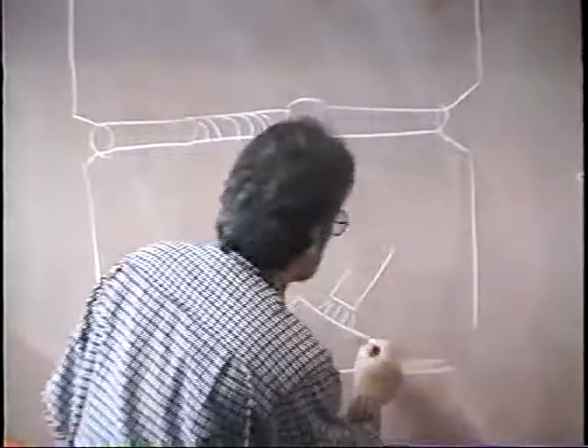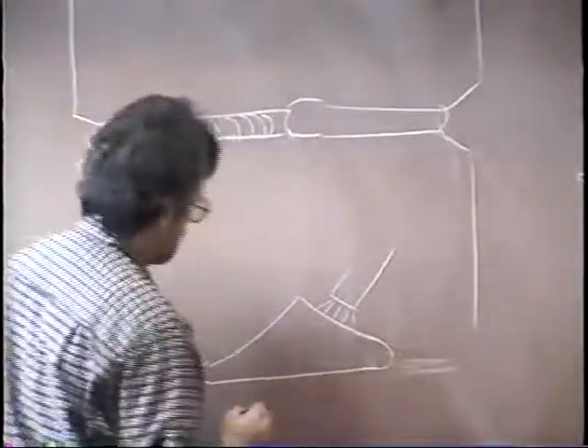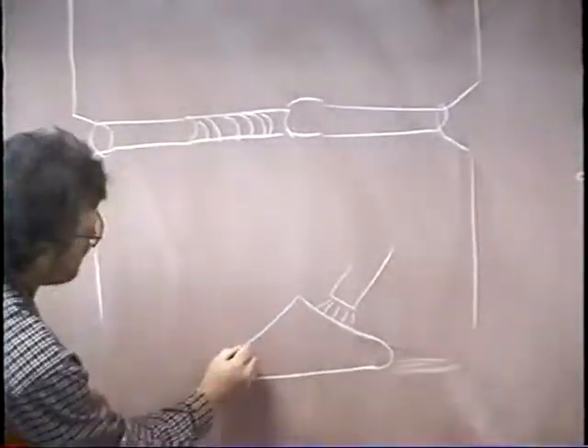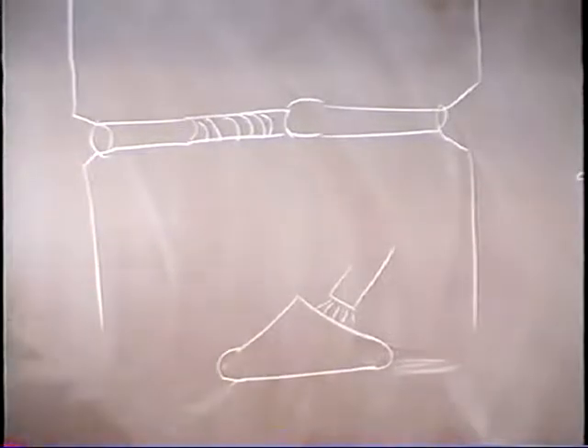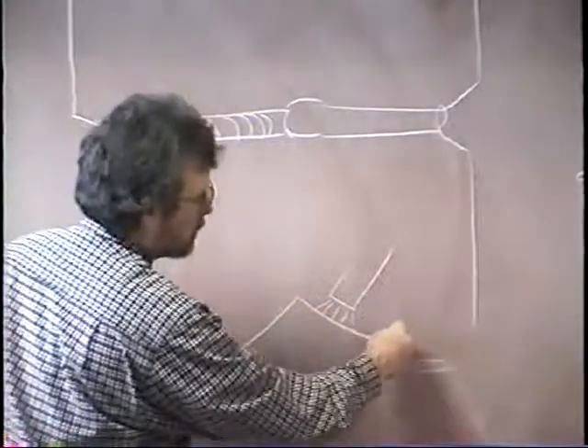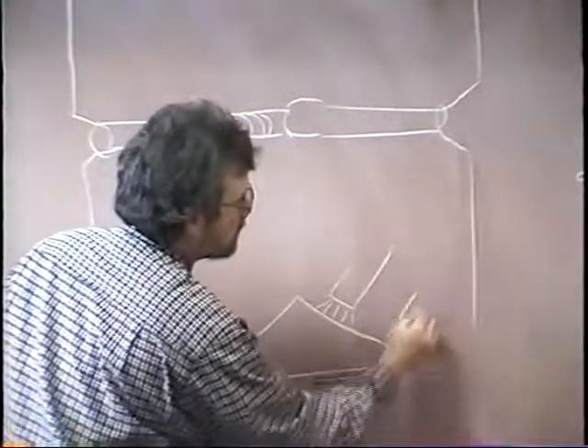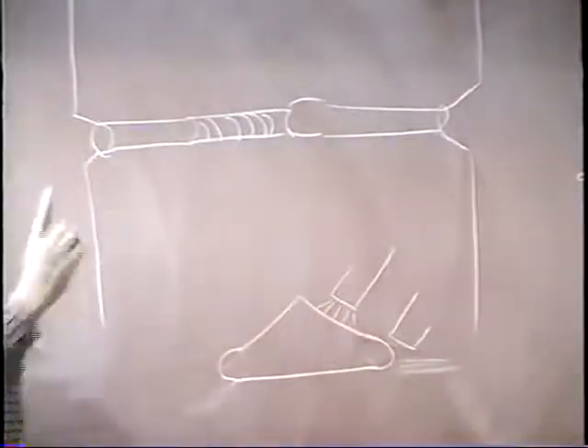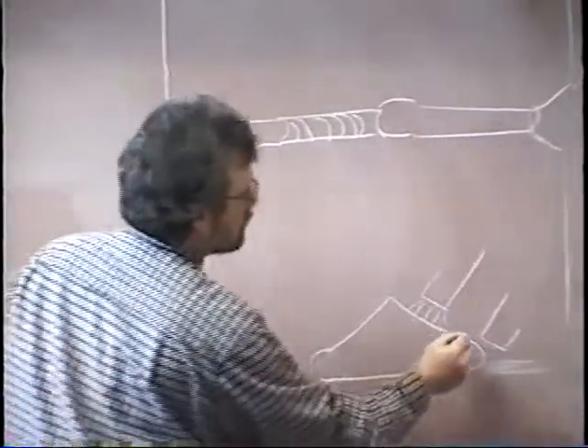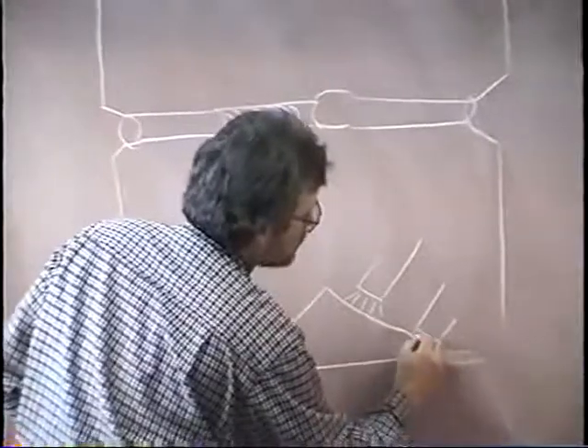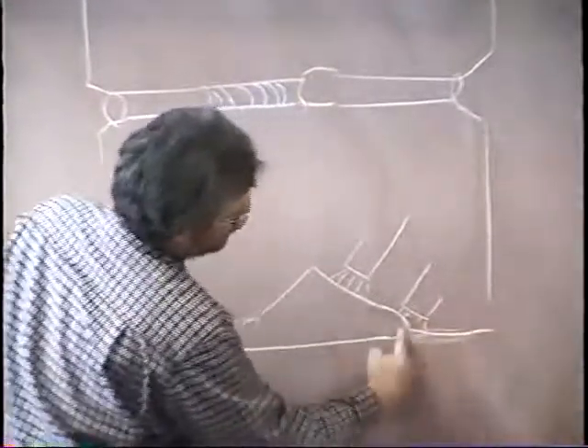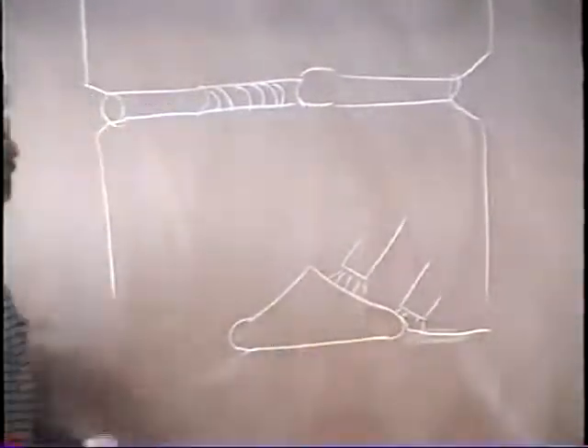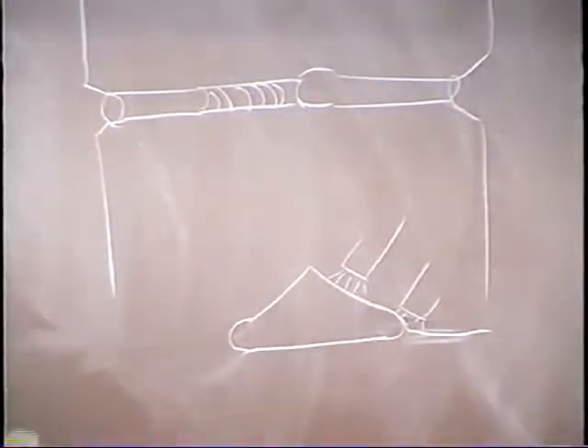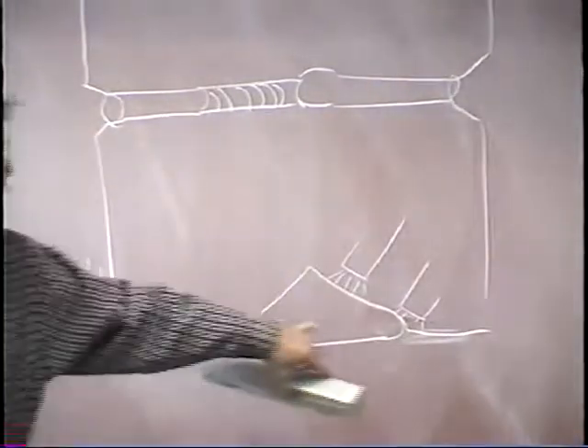If, however, you haven't feathered it properly, if your tack instead looks like this on the ends, and you come out and you're moving too fast, and this especially happens on the bottom of pipe in the 5G position, what happens is your weld picks up and you have a little void right here where you have lack of fusion. It didn't tie in. It didn't blend properly.